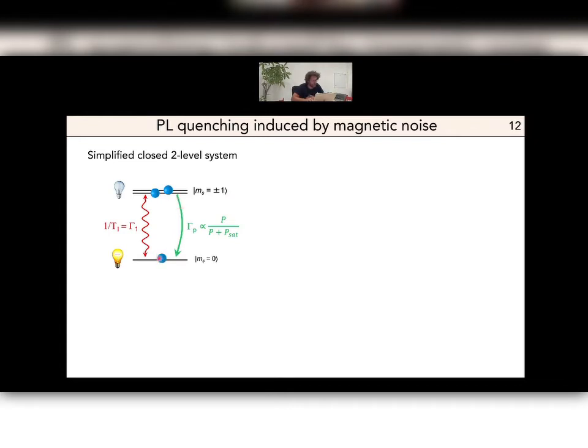And this is in competition with the longitudinal spin relaxation rate here, gamma 1. And we have essentially two different cases. When gamma 1 is much smaller than gamma p, then we have a very efficient polarization in ms equals 0, and as a result, we have a high photoluminescent signal. On the other hand, when gamma 1 takes over gamma p, then we have equal population in all the spin sublevels, and as a result, we have a lower photoluminescent signal.